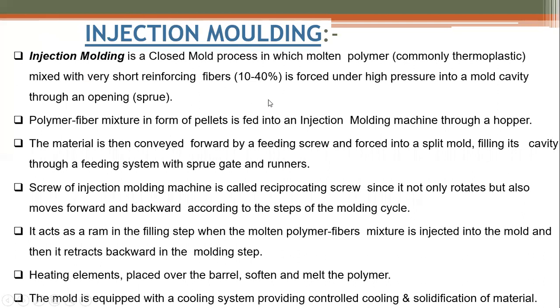Based upon the purpose, we decide on the reinforcing fibers, and this is a closed process in which molten polymer is mixed with the reinforcement. The molten polymer commonly used is thermoplastic only. We are not using thermosetting resins, because for the recycling process we commonly use thermoplastic resins only. These are mixed with short fibers and then forced under high pressure into a mold cavity through a sprue.